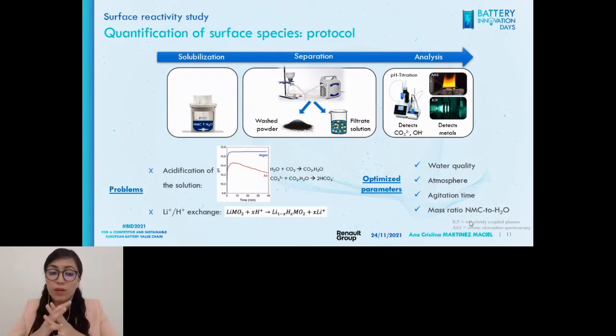We encountered some problems, of course. There was acidification of the solution, and there was lithium-proton exchange on the surface of NMC. So we had to optimize various parameters, such as the atmosphere, the water quality, the agitation time, and the mass ratio of NMC to water, to finally obtain a very reliable protocol that gave us reproducible results.